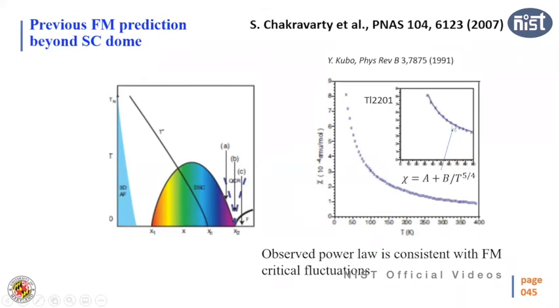As a function of temperature, if it is a paramagnet, it should be just inversely proportional to temperature. But instead of that, it shows this odd power law behavior. Now, this power law behavior, 5/4, could be possible if there are ferromagnetic critical fluctuations. Based on this data, he predicted that there is probably ferromagnetism at low temperature.